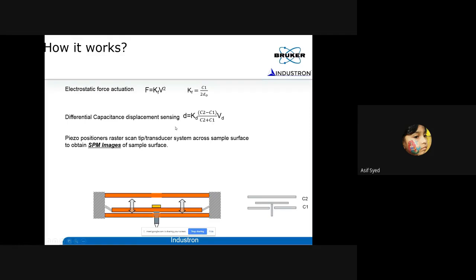I also mentioned that we can measure the change in capacitance and then convert it into displacement. This is the equation for that. Because there are two outer electrodes and a central electrode, you can form two capacitors, C1 and C2. So if you take the difference and divide by the total capacitance, multiplied by the voltage that you apply, it directly converts into displacement through a calibration. The force and displacement can be measured this way, and we can get the load displacement curve that I presented just a little bit ago.